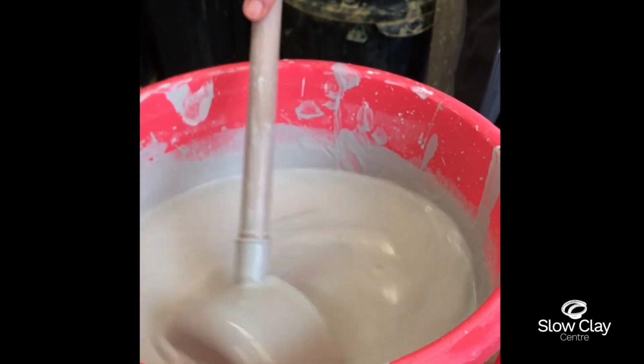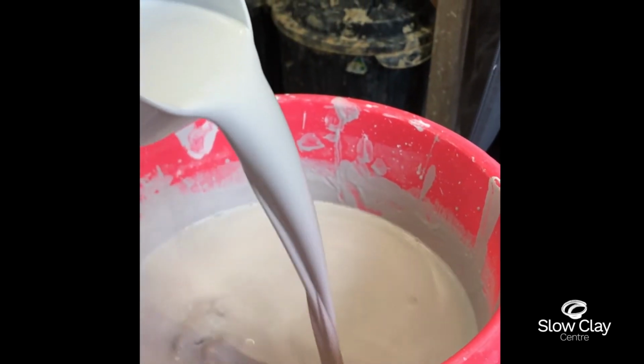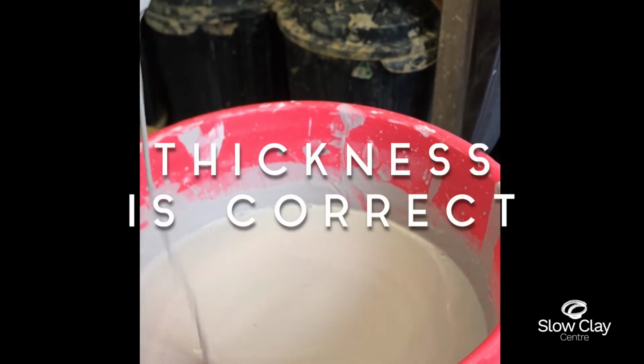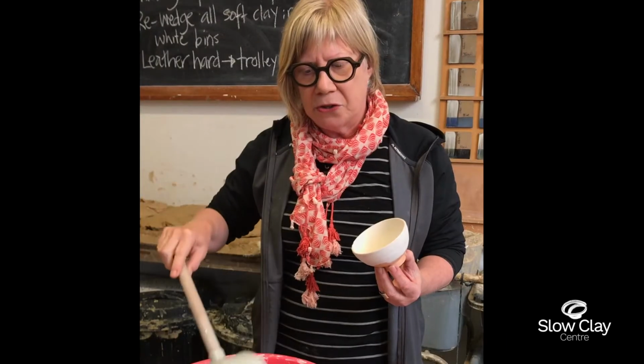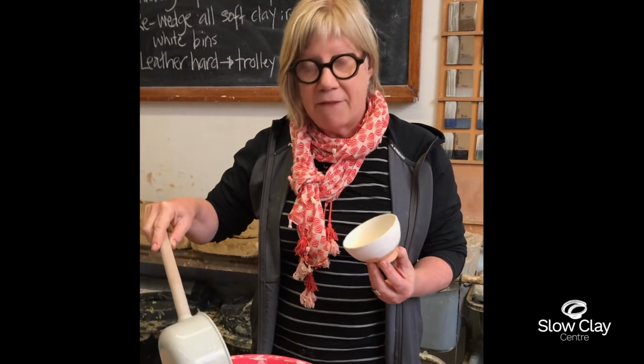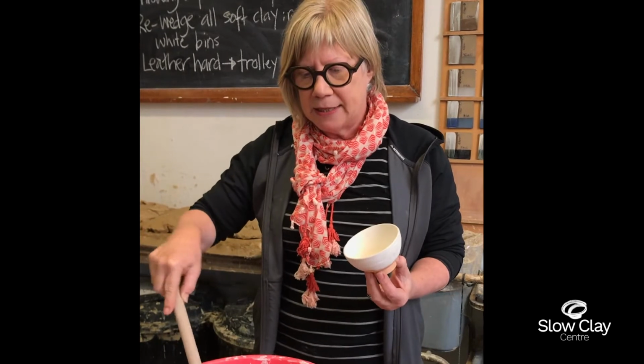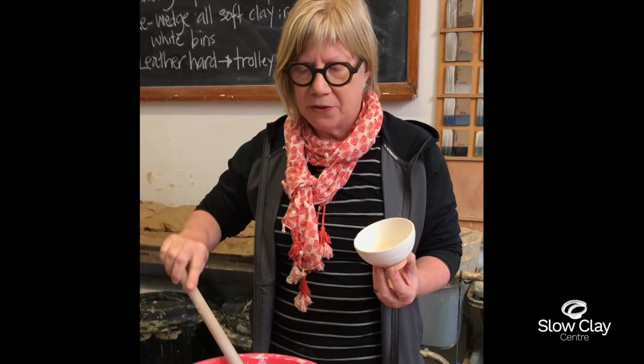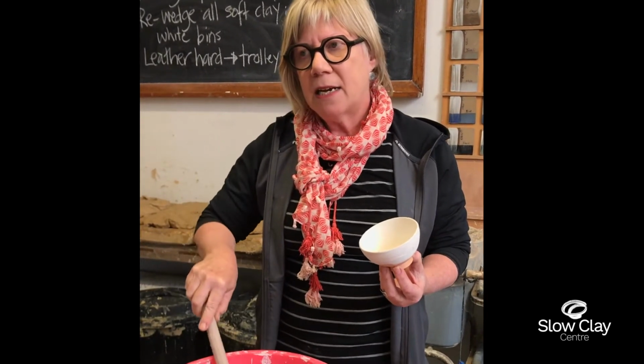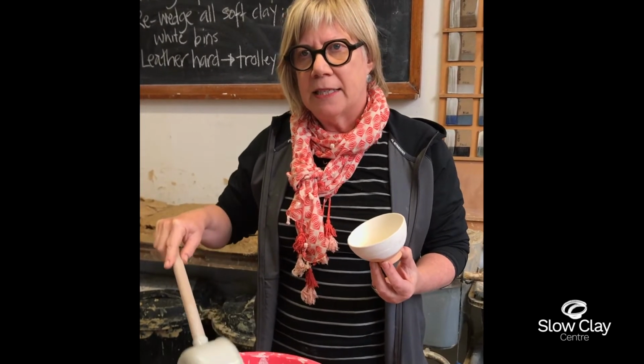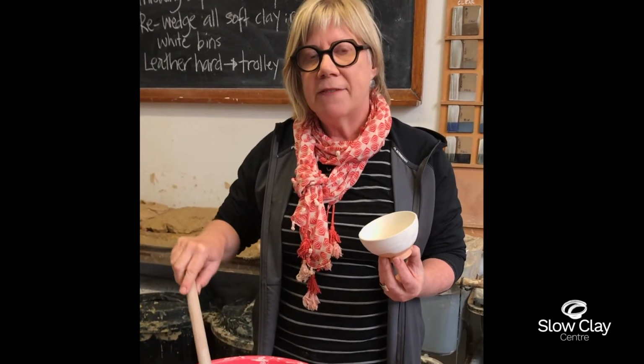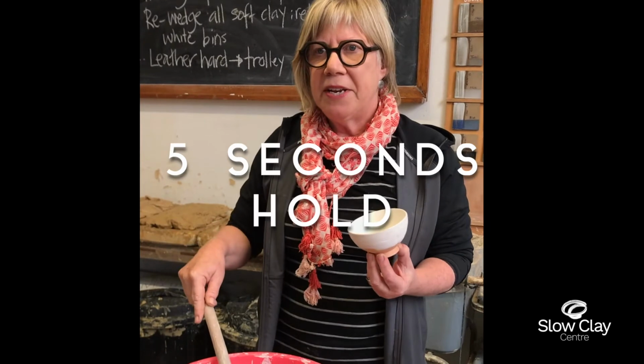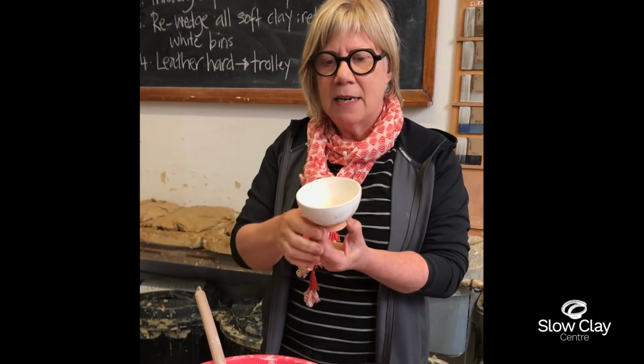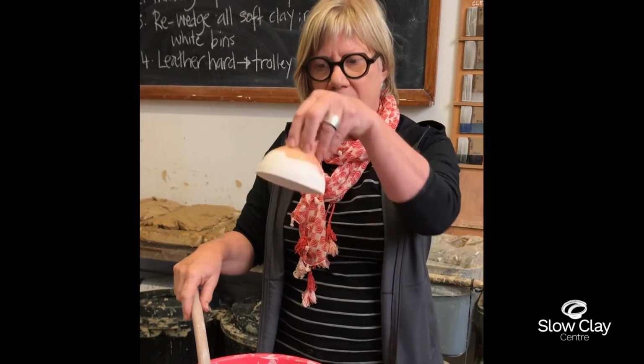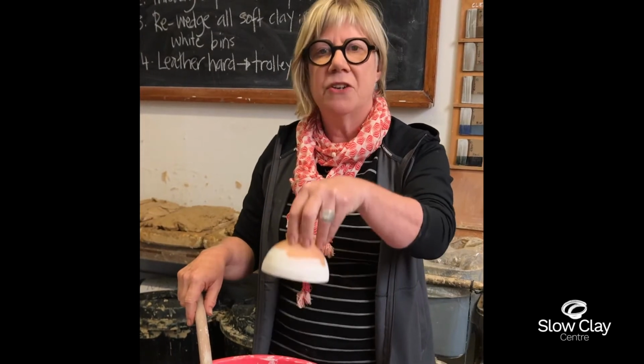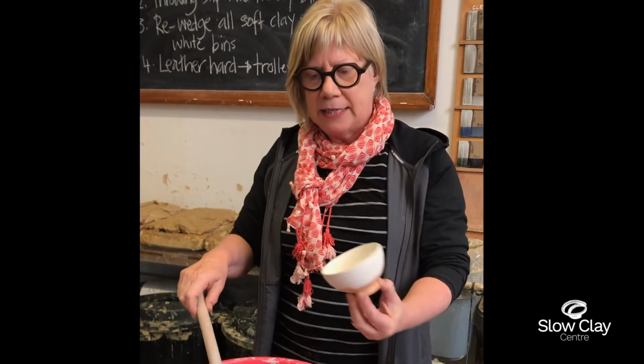We also double check that the thickness is correct and that the glaze is not too thin or too thick. And if it is too thick, I've actually added quite a bit of water into this one and thinned it down because it was on the thick side. And we mix our glazes up here at Slow Clay Centre for a 5-second hold. So that means once it's in and you're actually doing it, or once it's under the liquid, you're counting to 5. So let's just do that now.